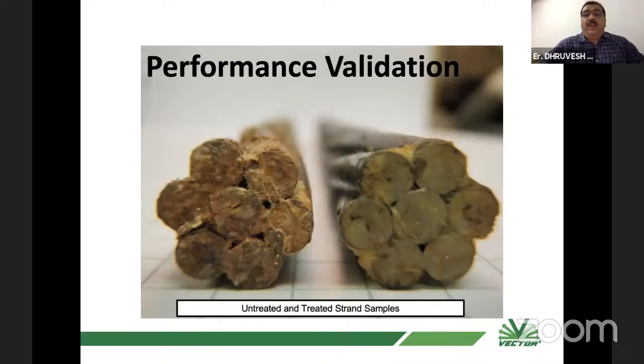Like we had a strand which is uncoated, untreated, and a strand which has been treated with impregnation material. We have a salt spray method, and we put them under the salt spray condition, and after a period of time, we had a full report if somebody wants. This is just to show what has been done. And we found that the strands which are untreated were corroding, and there was no issue on the strands which are treated.